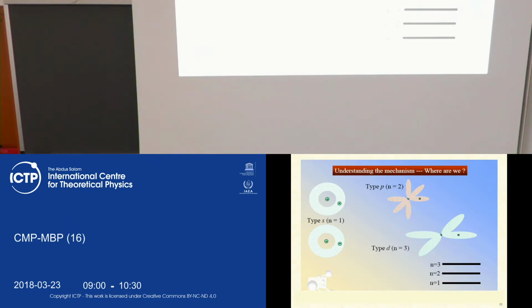the symmetry of the superconducting order parameter should not be spherical. What we discussed on the blackboard and what was discussed in the Bardeen-Cooper-Schrieffer theory was a spherically symmetric gap, which didn't even depend on the momentum, not to say angle, which was sufficient to explain the superconducting properties of simple conventional superconductors. However, in the high temperature superconductors, it was found that the symmetry of the superconducting order parameter is not S-wave. So the order parameter is not spherically isotropic, and after a very long debate, I remember I was like 20 years younger, it was a very hot debate about experiments and theory, whether it's still an S-type superconductor or something else.